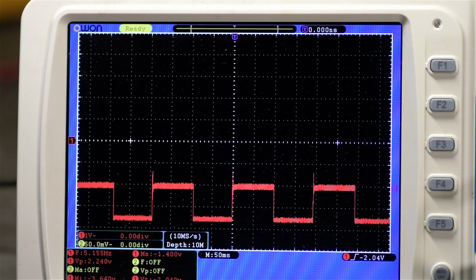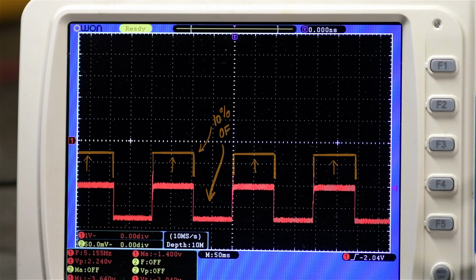But in fact, now that I'm looking at it, I think I see another problem. According to the manual, the base current of this machine should be 10% of the peak current. So since we're set to 40 amps, it should be 10% of that, 4 amps or 5 amps, which is the minimum the machine will do. Here it looks like it's more like 50%. It's at like 20 amps. That's both curious and sucky at the same time.